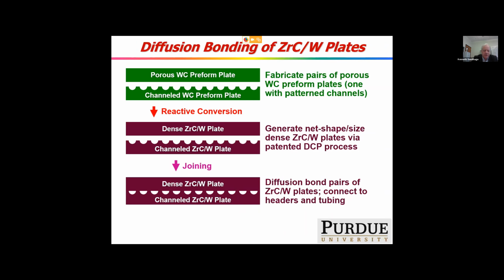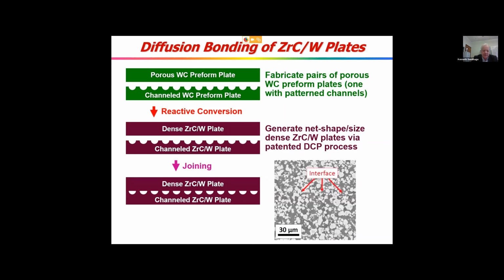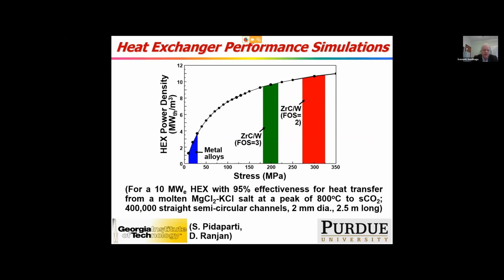We can also diffusion bond these materials together, as I mentioned, from the phase diagram. They do have some solid solubility in each other, and so that allows us to diffusion bond them. You can barely make out an interface shown there. We do this typically around 1400 to 1600 C, but it does diffusion bond quite nicely because of that solid solubility. So why are we doing this from an application standpoint?